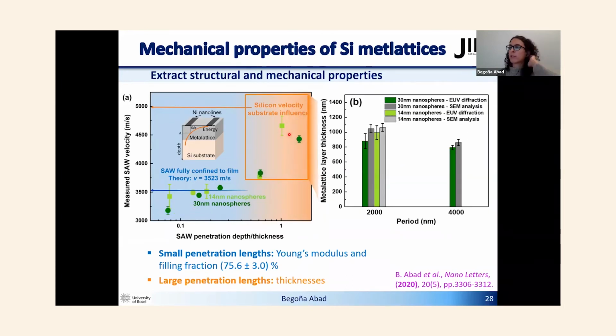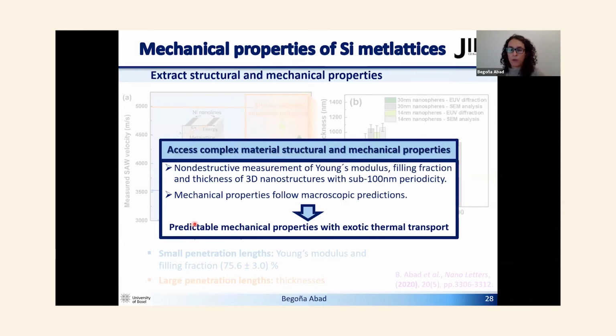But once we know the mechanical properties of our metalattice, we can also use the large-period gratings to access other types of information. In this case, as the waves are reaching the substrate, we can extract the thickness. We also compare with SEM, and we found that we could get this information in good agreement. So from this spectroscopy on this type of complex materials, we can say that we were able to non-destructively measure the Young's modulus, the filling fraction, and the thickness of these 3D nanostructures, which have sub-100 nanometer periodicity.